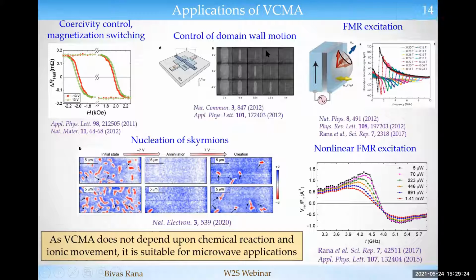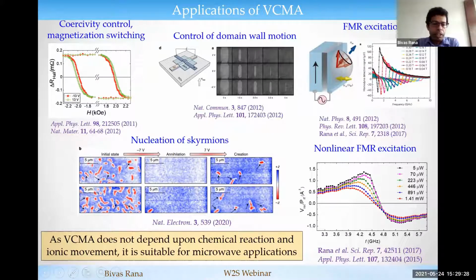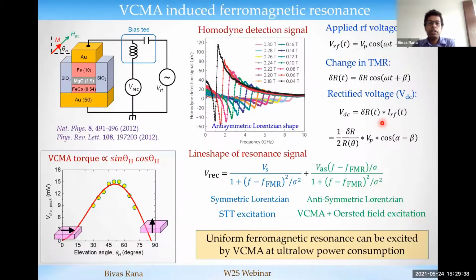Okay. So basically, one can excite the ferromagnetic resonance, and it can be either linear or nonlinear ferromagnetic resonance by this voltage control magnetic anisotropy. One of the important properties of this VCMA induced ferromagnetic resonance is that this VCMA torque is linearly proportional to the sine of the elevation angle of the magnetization multiplied by the cosine of this elevation angle. That means if the magnetization is aligned perfectly either in plane or out of plane direction, it is not possible to excite the ferromagnetic resonance or even the spin wave in the system. So that is one of the important features of this voltage control magnetic anisotropy.